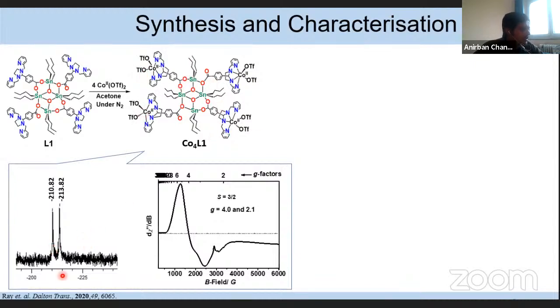tin NMR. Here in the tin NMR, for the complex, we see one doublet around minus 210 ppm and 213 ppm, which is exactly similar to the free ligand. So from the tin NMR, it is confirmed that the stannoxane core remains intact after complexation. And the EPR spectrum shows a high-spin S equal to 3/2 cobalt(II) center, and also from this EPR spectrum it is evident that the cobalt centers are not interacting with each other via any intramolecular interaction process.